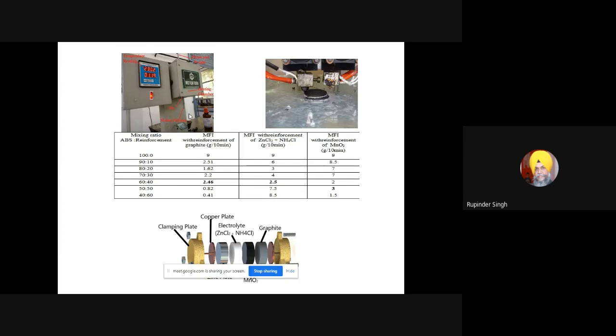So what we did, we selected ABS as a basic matrix material, and then we tried to put some quantity of graphite into it. Initially, with 100% ABS, the MFI was coming as 9. With the increase in the graphite proportion, like initially 10%, the MFI was reduced. Then again, with different proportions of the graphite, I got different values of the MFI.